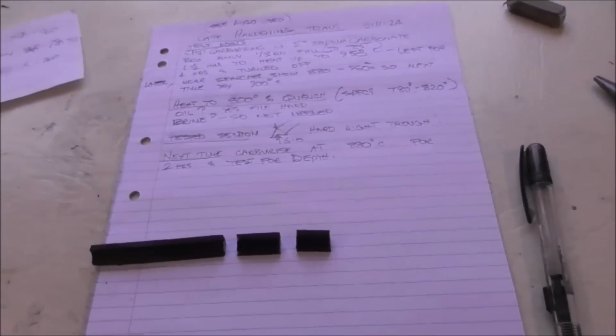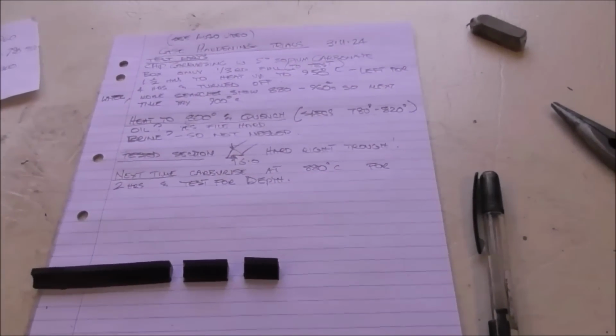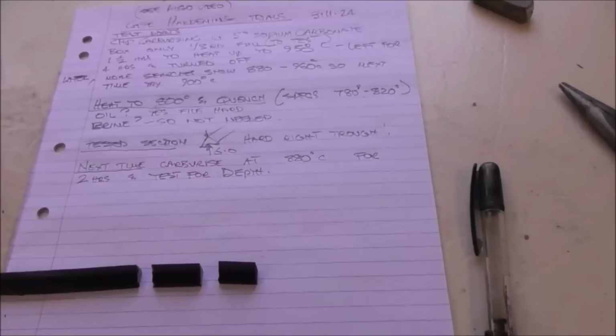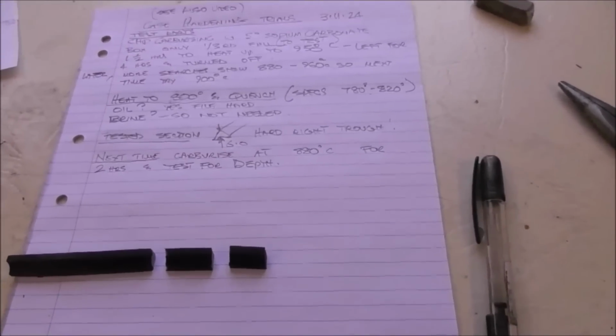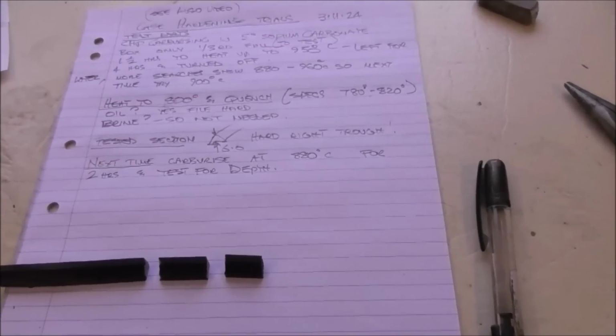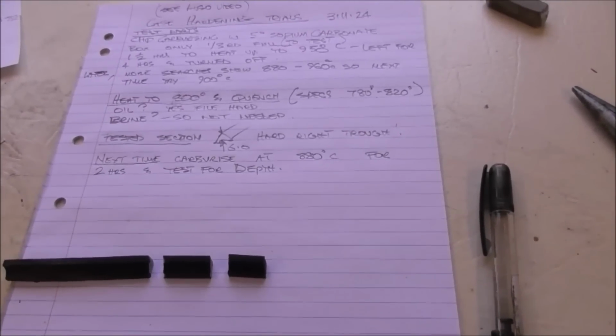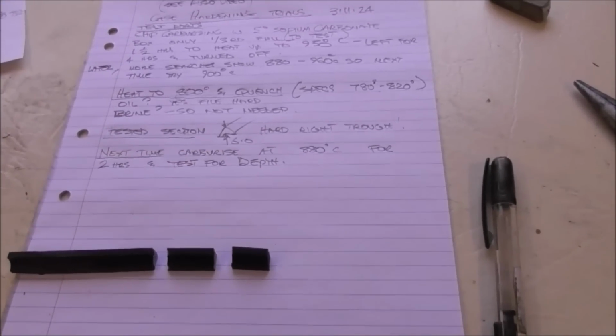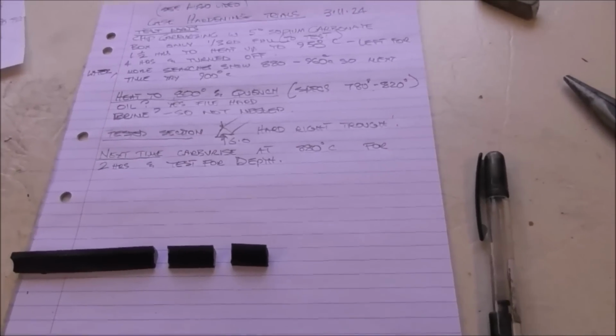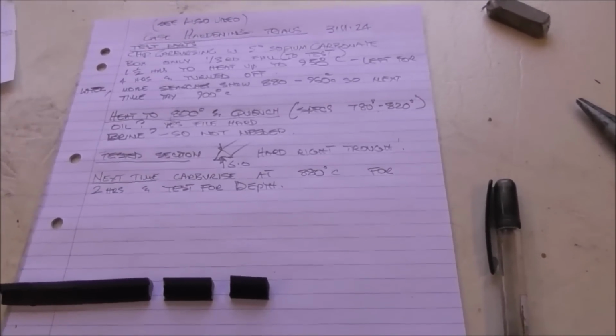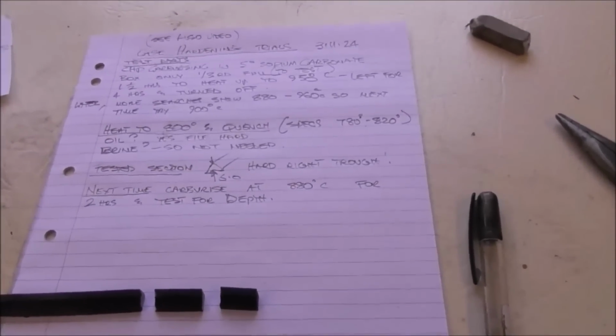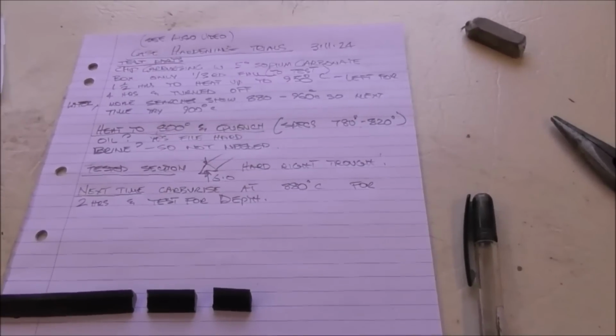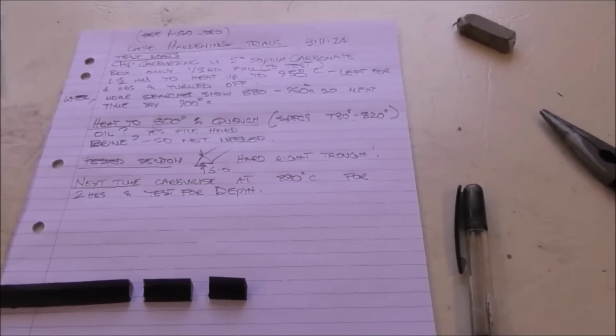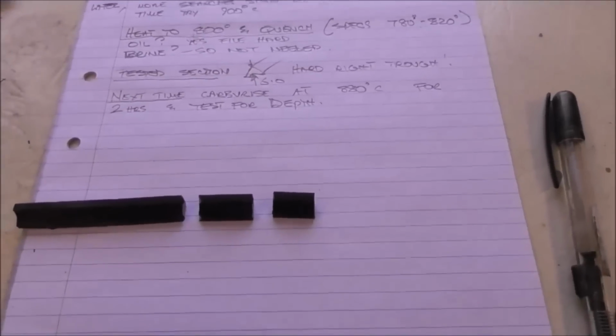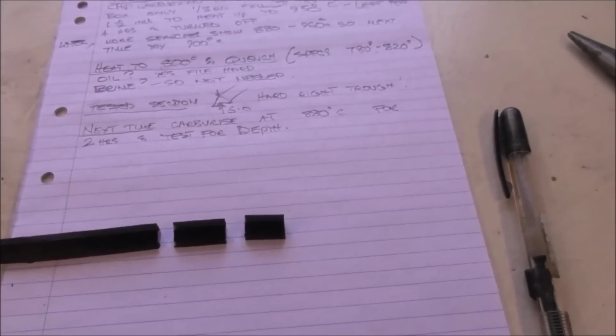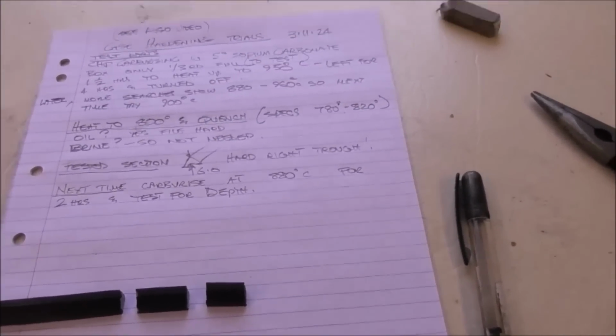So I think next time I need to carburize at a lower temperature at the bottom end of the range, say 880 degrees C, for a shorter period, say 2 hours, in a part that doesn't matter if the case comes out very shallow, because there's a lot of applications where a shallow case is fine, and then I can test to see how hard it is and how deep the case is, and I'll get some more information. But I got a whole heap of really interesting information from these tests.